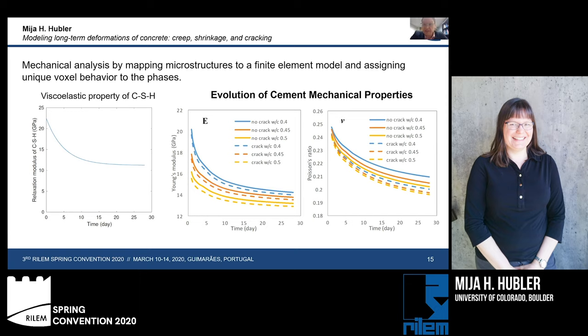Now, if I conduct a relaxation test by imposing a unit strain on my combined sample, I can observe the evolution of the cement mechanical properties, both with and without a crack. Here I've plotted the Young's modulus with and without a crack. No crack is the solid line. The dashed line is with a crack. And the Poisson's ratio with and without a crack. You notice the biggest effect on the Poisson's ratio happens, for example, for a water cement ratio of 0.4 if I introduce this one crack.